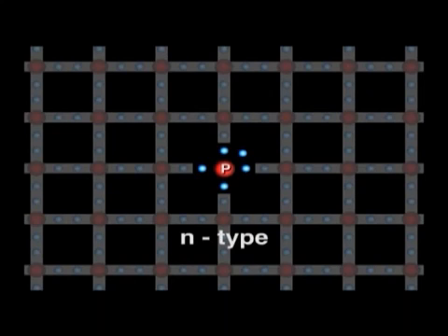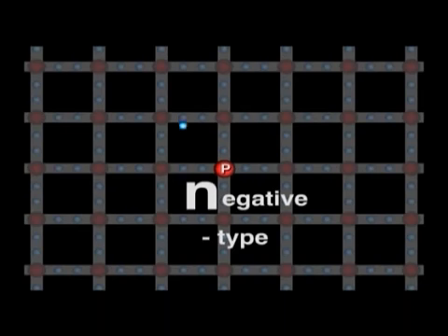When in the crystal, 4 of its valence electrons form complete bonds with neighboring silicon atoms. This leaves 1 extra valence electron that will orbit the phosphorus in a Bohr-like orbit at very low temperatures, but will diffuse through the crystal at ordinary temperatures. A phosphorus atom is called an electron donor because it donates an extra electron to the silicon crystal. Because the phosphorus atom has 1 more proton than silicon, it has a net positive charge. We will color it red to denote this extra positive charge.